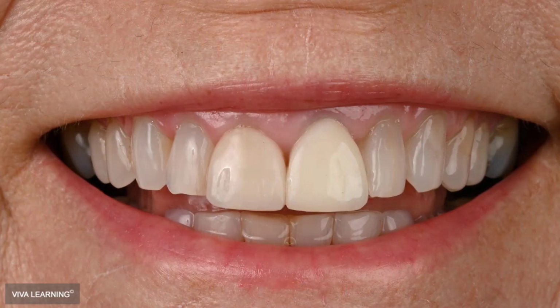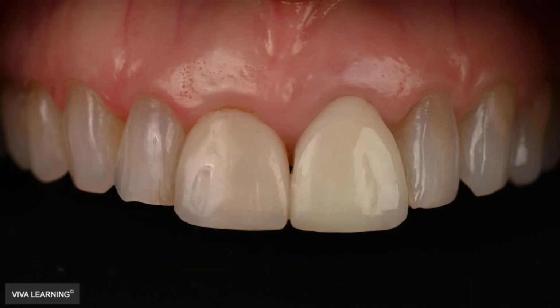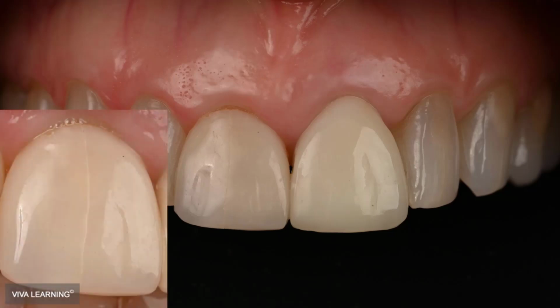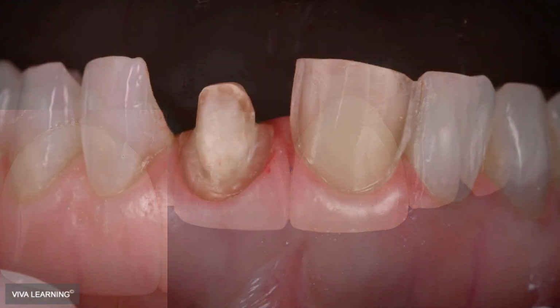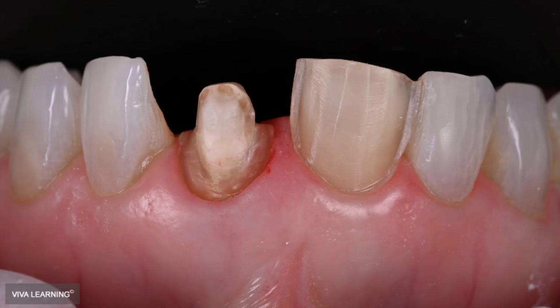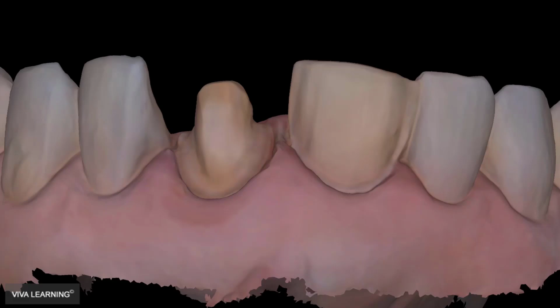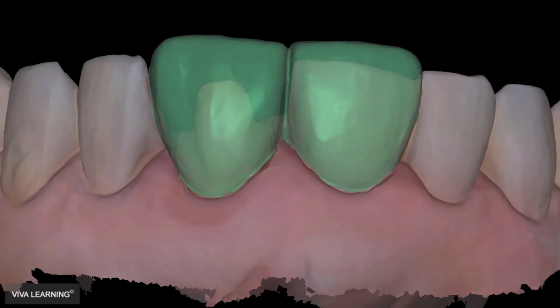Now, the importance of cement shade, and which cement shade we select, becomes more evident when we have a case like this. When we take a look at this case, the patient is not satisfied with the mismatch between 8 and 9. And also we can see that the veneer has been fractured. But when we analyze the case after removing the restorations and merging it into a digital world to understand what possibly was the reason that this mismatch has happened, we come to one aspect.